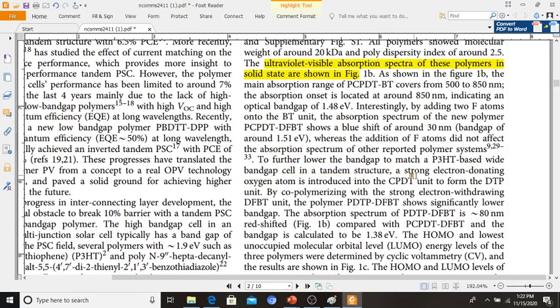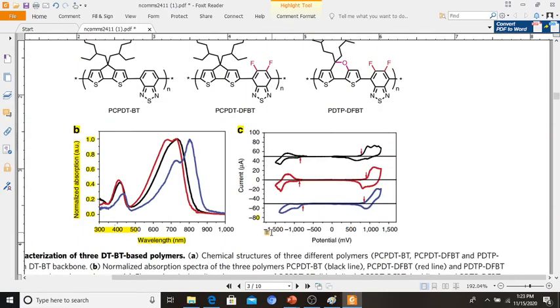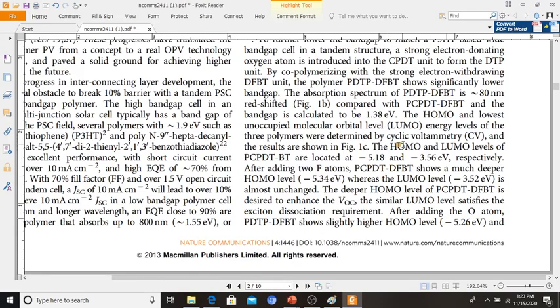For wide band gap cells in the tandem structure, strong electron donating oxygen atoms were introduced into the CPDT unit to form a DTP unit, by copolymerization with the strong electron withdrawing DFBT unit. The polymer PDTP-DFBT shows a significantly lower band gap. The absorption spectrum of PDTP-DFBT is around 80 nanometers red shifted. So you can see the lower band gap here, and that is represented here. The calculated band gap size is 1.38 electron volts.